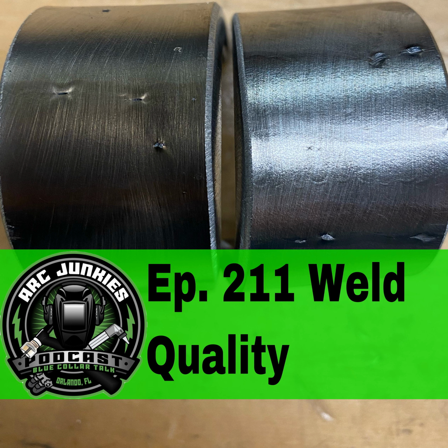The next one up is clustered porosity, and that is a local grouping of pores that result from improperly starting or stopping the weld. So that's going to be either at the beginning or at the very end in the crater. So one thing you can do to fix this is try not to speed up too quick. Strike your arc, let it burn in for a second, and then start moving through the puddle, and then make sure that you fill in your crater completely once you get to the termination of the weld. Also, you want to make sure that you don't have any cross breezes or anything going that's going to blow your shielding gas out of the way. That's pretty much what's going to cause clustered porosity.